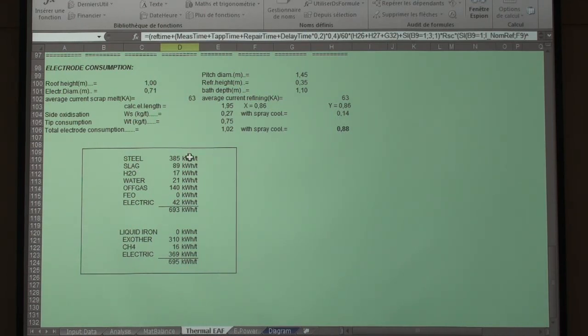Here you have the liquid steel enthalpy, the energy of the slag. This is the energy absorbed by the water, I mean the water in the scrap. I've put this here, but it could be included in the off-gas itself. This is the water-cooled panels. So the slag usually is in the range of 60 to 80 kilowatt hours per ton, depending on the scrap cleanliness. Water-cooled panels, it's in a range of 35 to 40 for good furnaces.